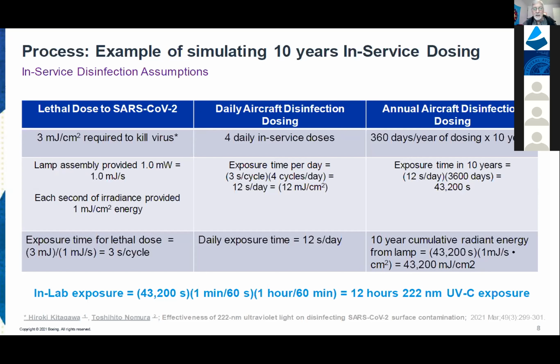So we then rounded up, because at Boeing, we love to round up. We like nice whole integer numbers. We said, okay, that's a good estimate. Let's say an airline is using UVC light to disinfect and they want to kill the virus. So let's also assume now, just in this example, that their lamps have an irradiance of 1 milliwatt per square centimeter. Okay, you need 3 millijoules to kill it. So that means 3 seconds. That's it. So you hold the lamp at the point where it's 1 milliwatt per square centimeter over the surface, wait for 3 seconds, boom, you move on. That area is clean and virus-free.